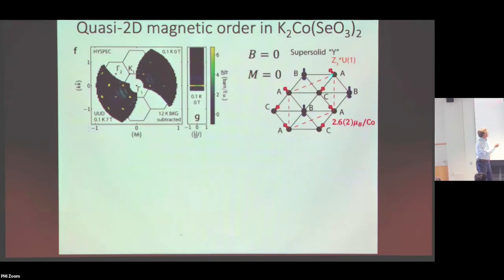And so that means that, if this is like a down spin, then these 2 red sites need to have half of the projection along the z-axis of a moment. So this is like a full moment pointing down, and then these will be 2 half moments pointing up, and they're actually canceling out the z-axis component. This in-plane component is something that we infer from the spectroscopy. I'm going to get back to that. It's very important for the identification of the nature of this low temperature state.